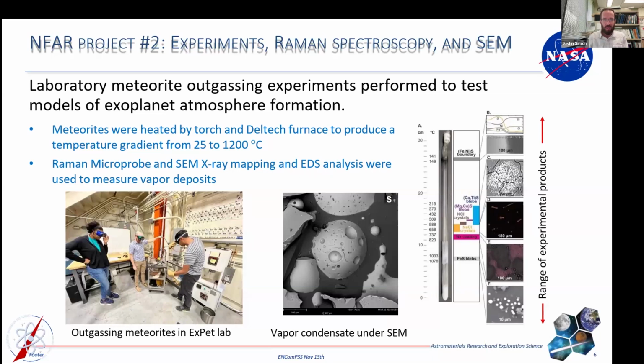So this example, project number 2, highlights a creative experiment, or a series of experiments, that were run by our experimental petrology group, our experimental analog group. In this case, this individual was interested in outgassing to model the various processes for exoplanet atmosphere formation. They were utilizing some of our expertise, but also some of the different heating and experimental devices that we have. And then they subsequently measured the different reaction products with Raman and the SEM.